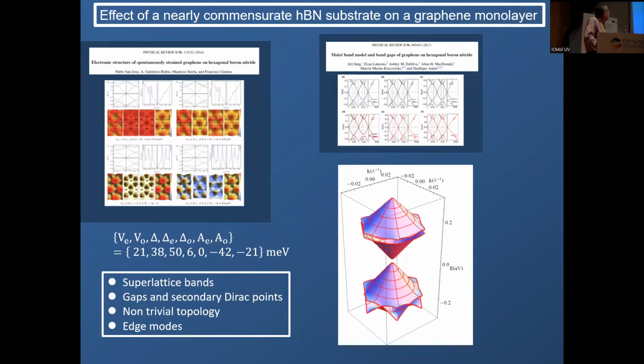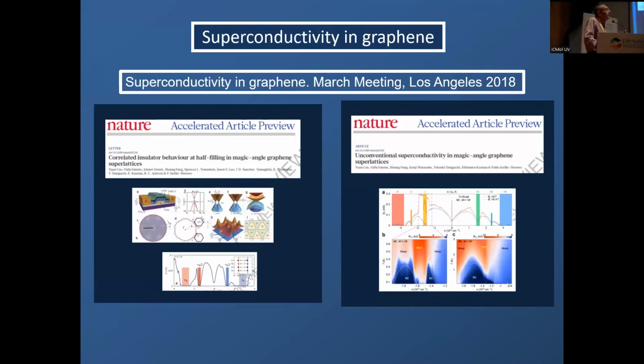Okay. Now let's go back to superconductivity in graphene. The group of Pablo Jarillo-Herrero was trying to make moire patterns by a different route. The thing is, instead of aligning graphene with a substrate whose lattice constant was close to the graphene, they thought, well, maybe one can make a moire by putting two graphene layers one on top of the other, but not perfectly aligned.